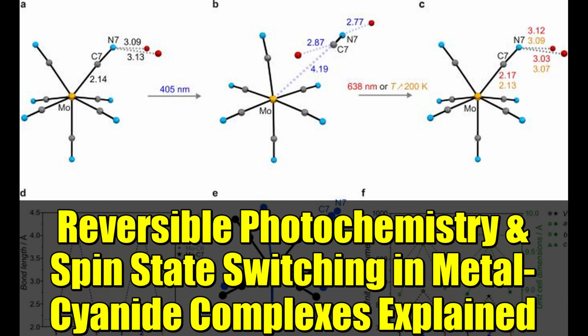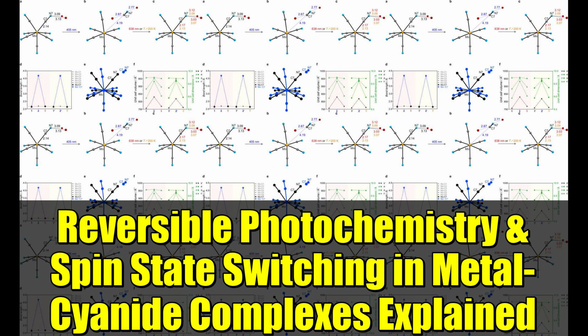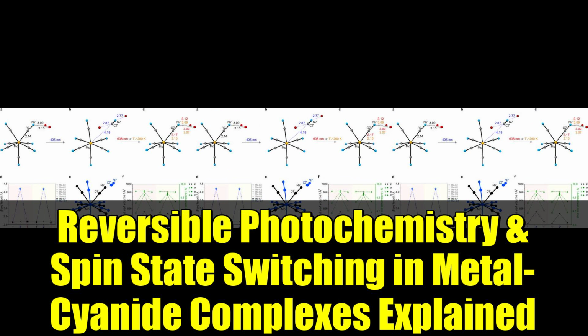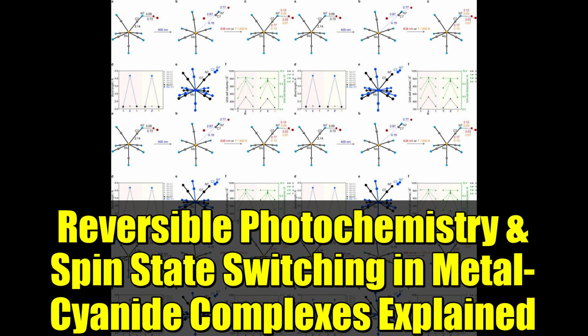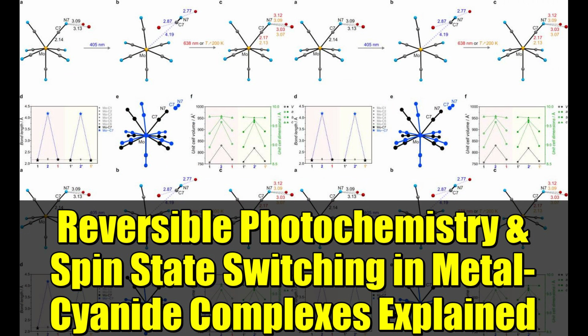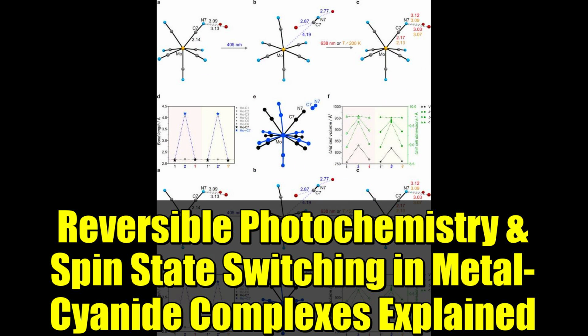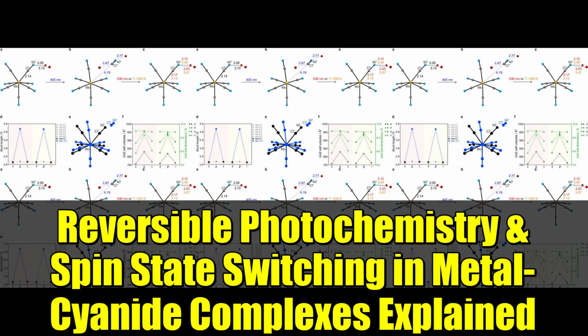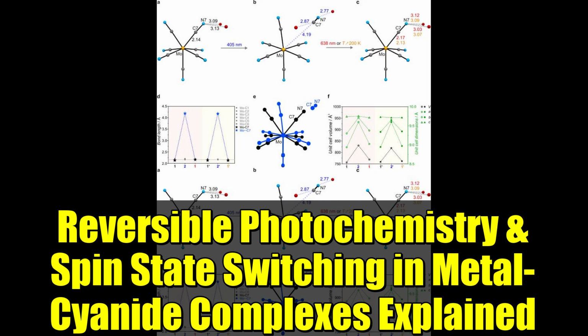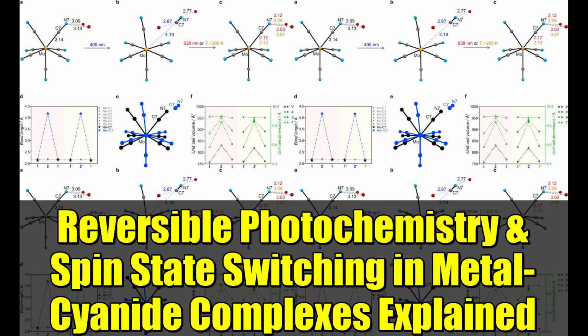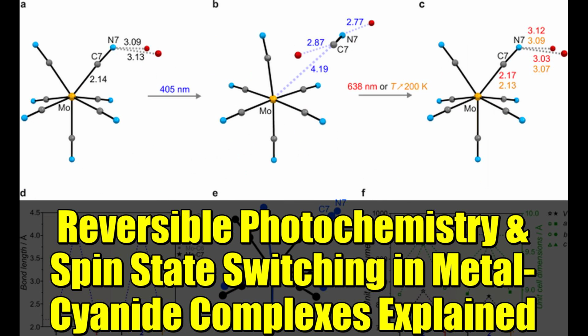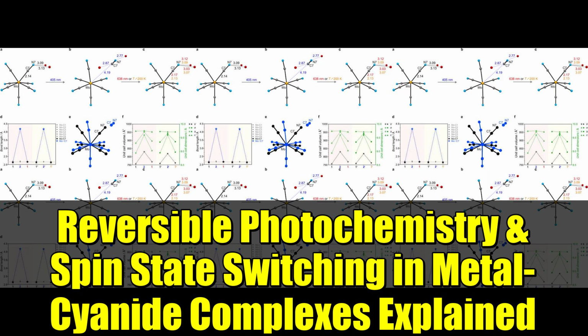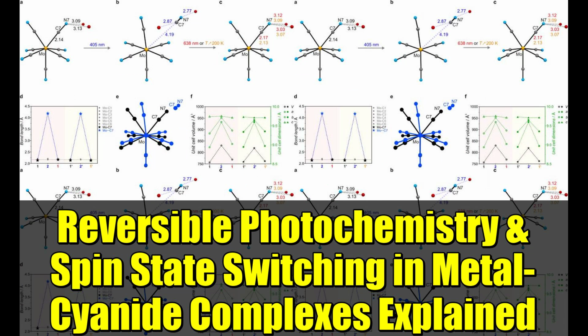The photochemical switching behavior of 1 was thoroughly characterized using a combination of techniques, including single crystal X-ray diffraction, SCXRD, infrared, IR, and electron paramagnetic resonance, EPR, spectroscopies, optical reflectivity studies, and X-ray absorption spectroscopy, XAS, complemented by magnetization measurements and X-ray magnetic circular dichroism, XMCD. The results revealed that the photodissociation of Mo(III) [Mo(CN)7]4- leads to the formation of Mo(III) [Mo(CN)6]3- and a free CN- anion trapped between H2O molecules and K+ cations.